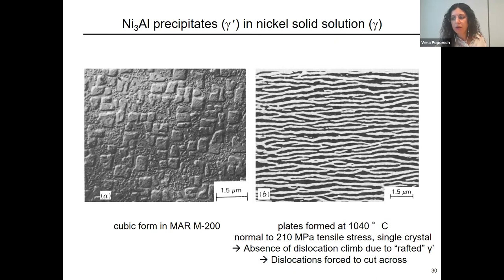And this kind of gamma prime is ordered. They have an ordered structure, a specific cubic form structure, and it's very difficult for dislocations. So when the dislocations want to move in the material, and we know that for deformation, dislocation motion is required, it's difficult to move past these particles because the order will be reduced.